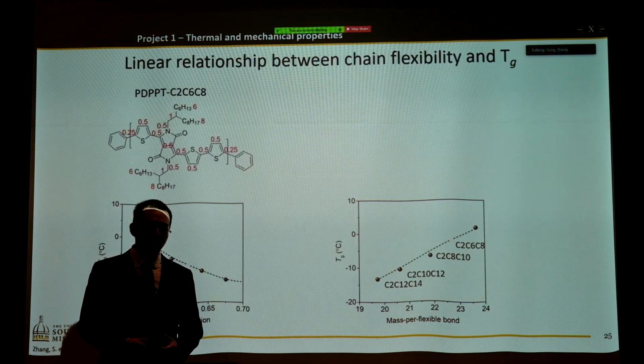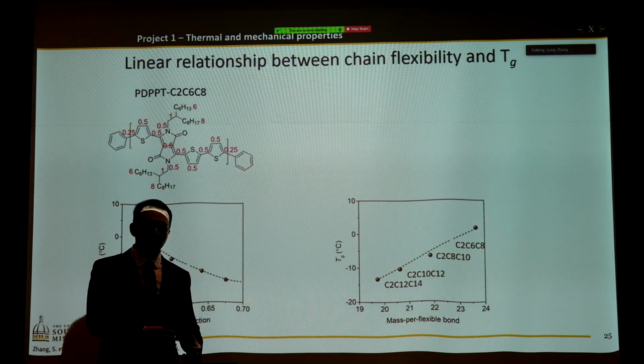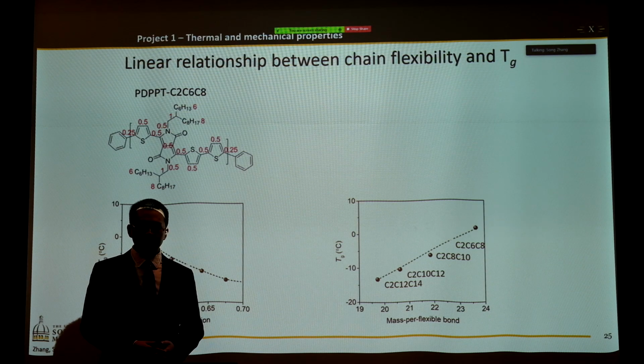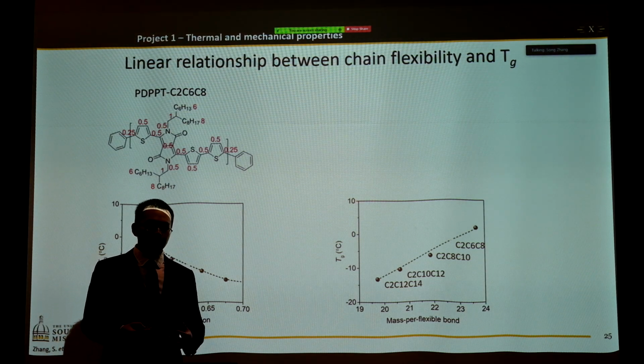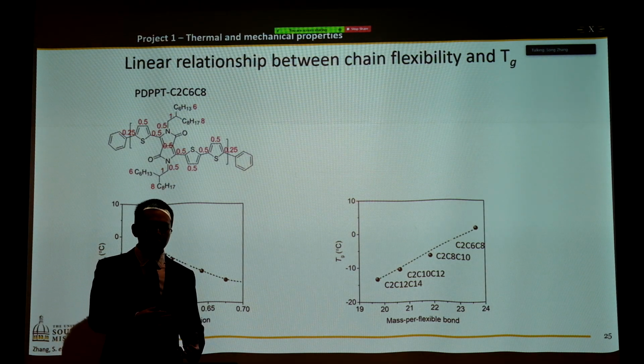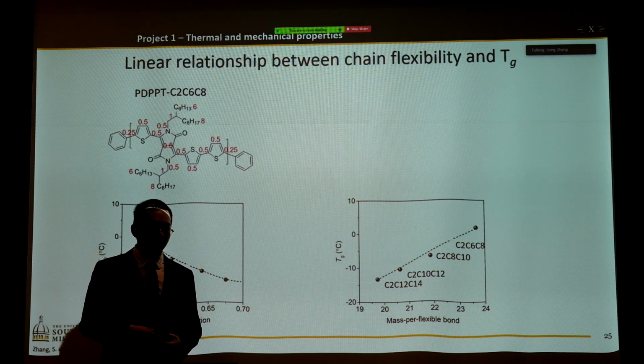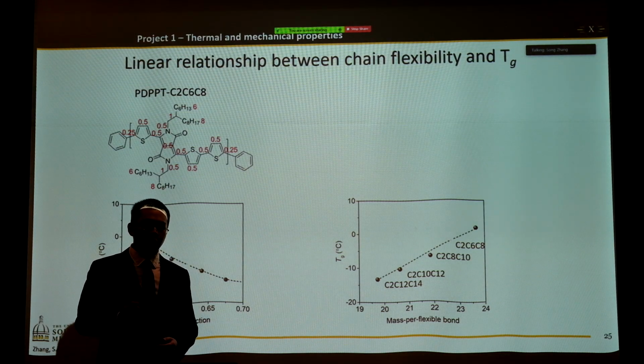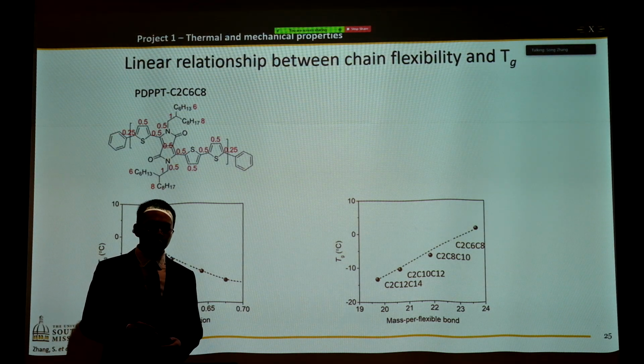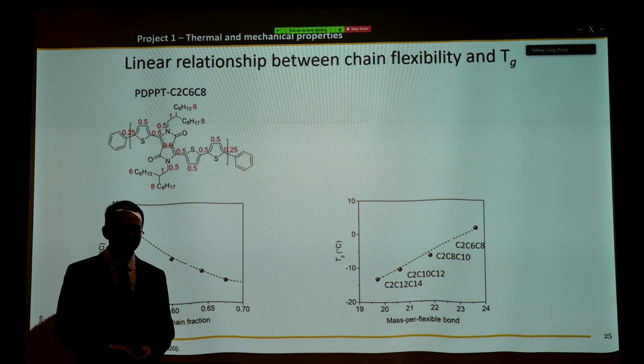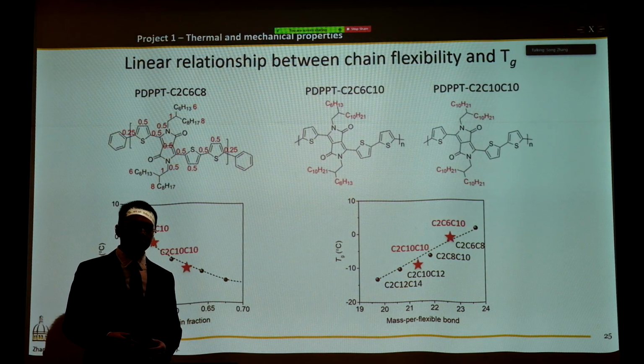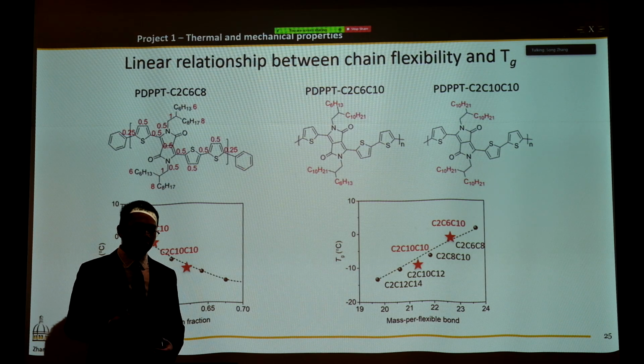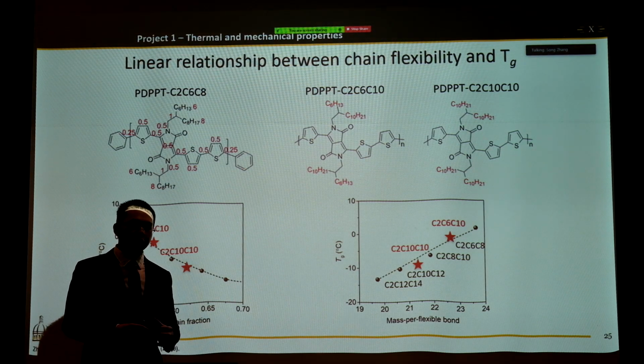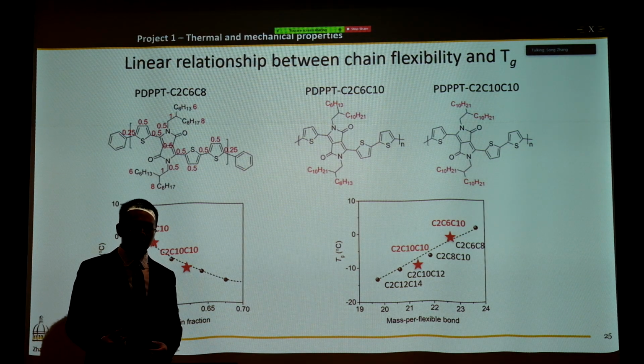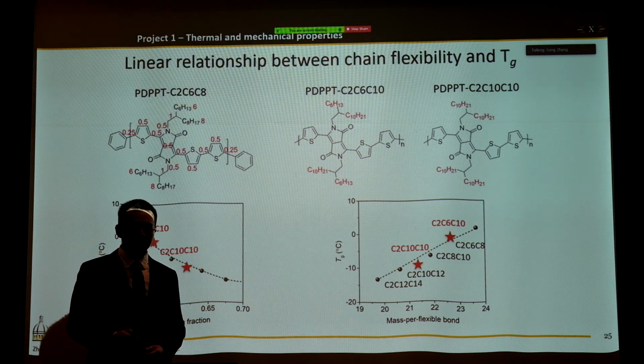Okay, now we are getting very excited and apply it into the 4 polymer systems we mentioned before. On the left shows the typical simulated result. The Tg is decreasing with side chain fraction. And on the right is a linear fit of these 4 polymers into the mass per flexible bond model. If we add 2 more polymers with intermediate side chain, it's still valid and makes this linear fitting have a very high confidence of 98%.